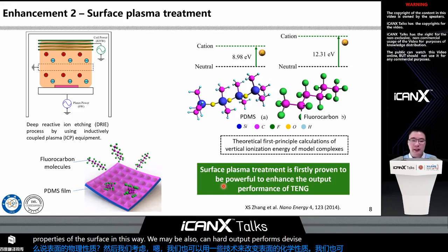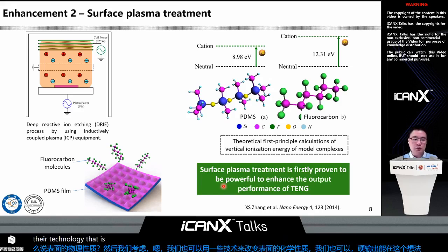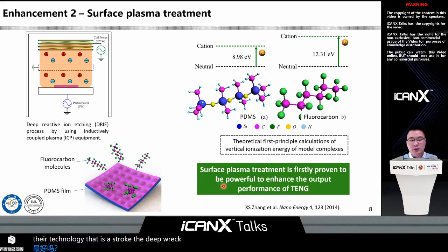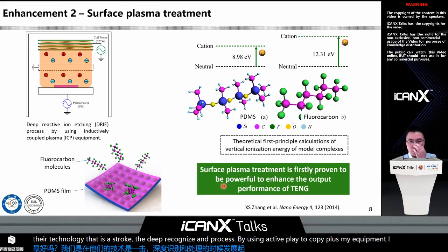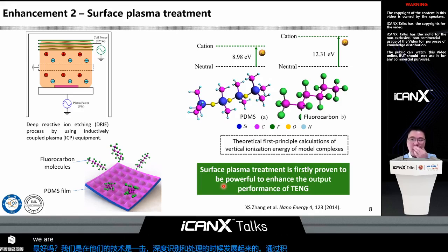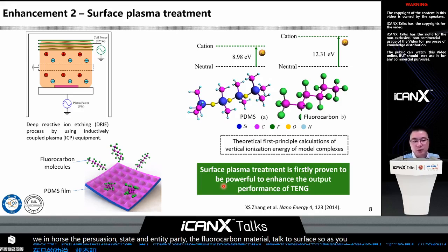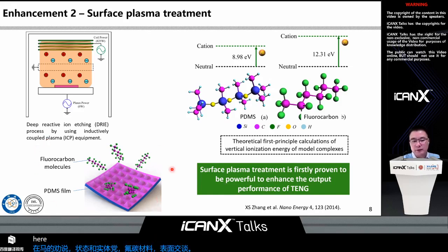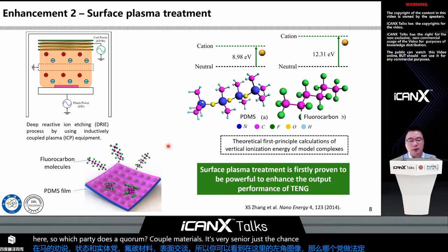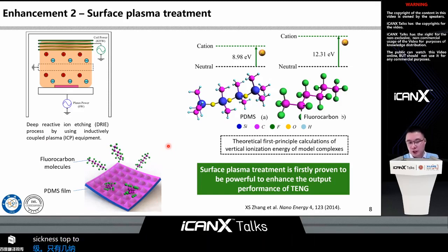So based on this idea, we developed one technology that is still through the deep reactive ion etching process, by using the inductively coupled plasma equipment, the ICP equipment. So we enhanced the passivation step and then deposited the fluorocarbon materials atop the surface. As you can see at the left corner image here, we deposited this fluorocarbon material. It's a very thin layer, just tens or several nanometers in thickness atop the surface, and then you can change the chemical property of the surface completely.